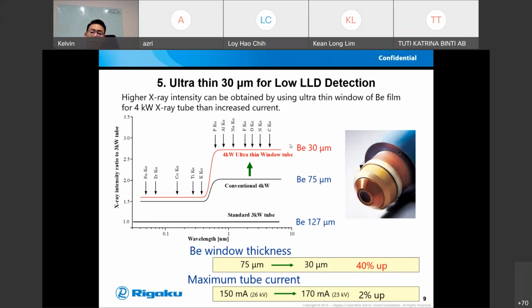So as you can see in here, different thicknesses of the window affect the intensity of the X-ray. Which means by having a 30 micron tube, the relative intensity of the system is affected very largely for the light elements in here. Compared to the conventional 75 micron tube itself, the intensity that you can see from the measurement is going to be higher.